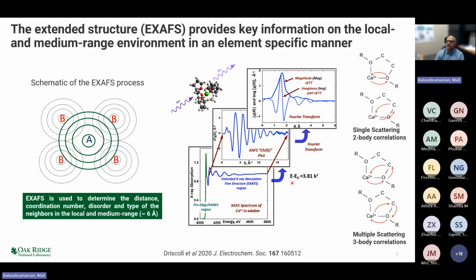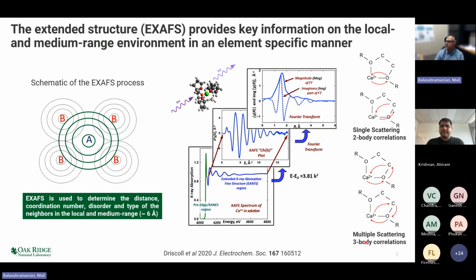So the kind of scattering that you can expect, as in this example for this calcium, is that you can have this calcium-oxygen interaction or interaction between the calcium and this carbon. So these sort of photoelectron scatterings are called single scattering processes, and it involves two-body correlations. You can also consider the photoelectron bouncing off more than one atom. For example, it could bounce off the oxygen, go to the carbon, and come back to the calcium. When that happens, you have more than two-body correlations. Essentially, in this case, it's a three-body correlation.